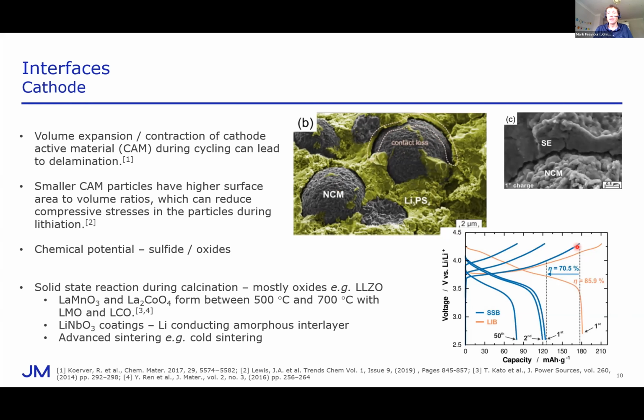And that is reflected in this initial data here. There's a 30% reduction in coulombic efficiency on just one cycle. This is the blue data. It charges up, and then you discharge it here, the first discharge, and you only achieve 70% of your coulombic efficiency because of the delamination effects, and that can carry on and on until you've got significantly worse performance. Now, I personally think this is an area that hasn't achieved much attention in the open literature, and I would say it would be nice if the ceramics industry could focus on that, as well as the chemistry industry, chemical academics and whatnot.